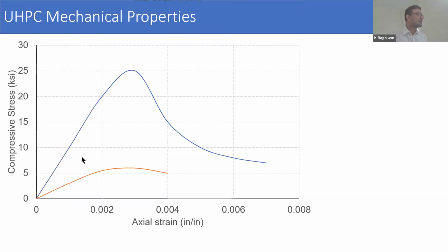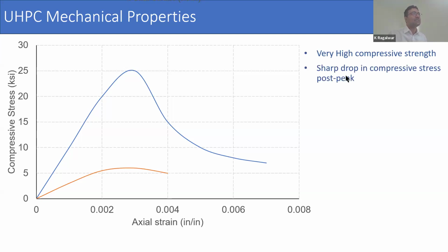However, the UHPC has distinctly different behavior in compressive strength. It is almost linear until it reaches its peak, and then after the peak is arrived, it sees a sudden drop. So this is an idealized curve, and that's why when I plotted it with Excel, it gives me a very smooth plot. But you would see that the fall after the peak is very sharp. So the compressive strength is very high in UHPC. We see a sharp drop in compressive strength after post peak.